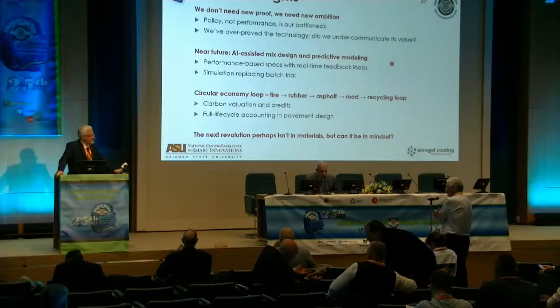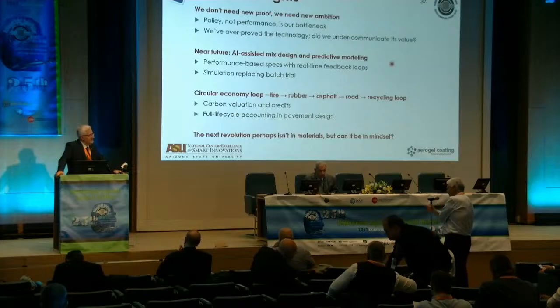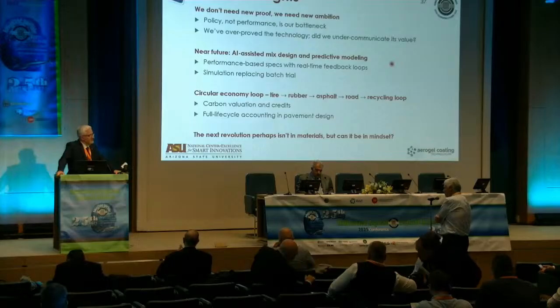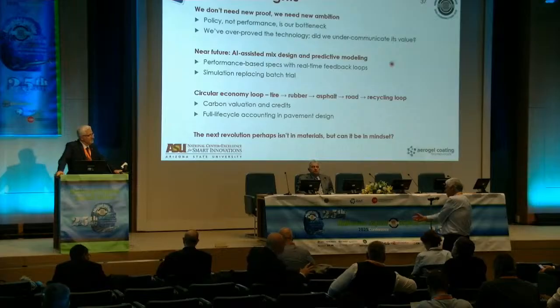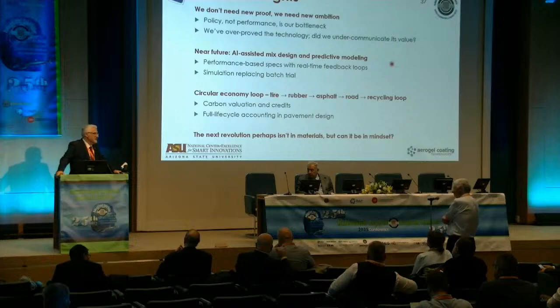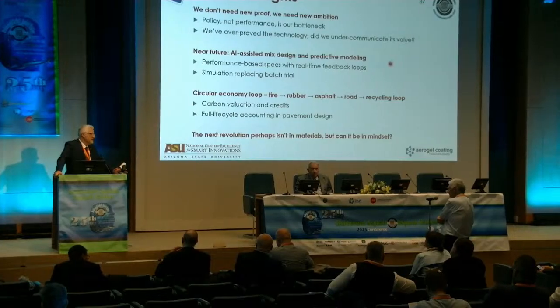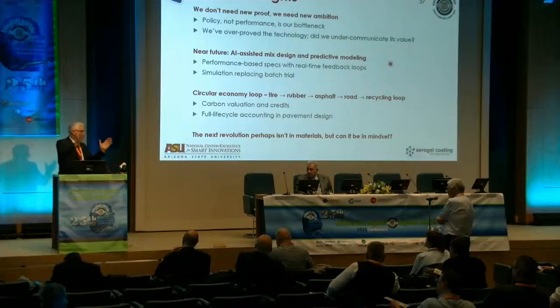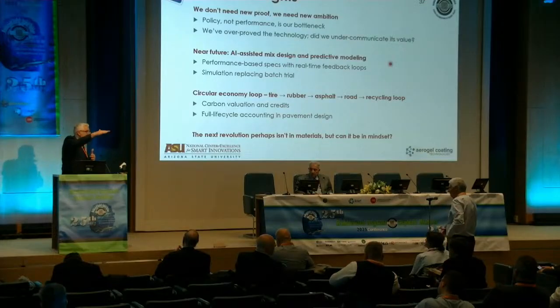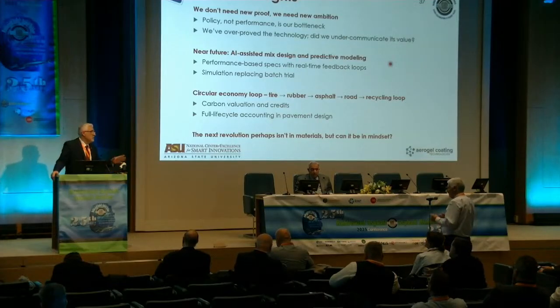How do you feel when you look at this product with aging? You live in a very extreme location for the aging of materials. If you say 1 year, 2 years, 3 years, 5 years of aging of material, how do you feel it might perform? So we don't have a lot of data on aging yet. This is coming. But anytime you reduce thermal stress, you would expect, logically, to have less aging compared to a conventional mix. I look at extremes usually in the way I think: if I can shield temperature from a pavement completely, there's no aging going to take place, or minimal aging going to take place.